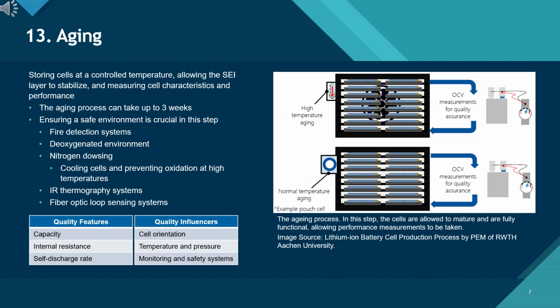Step 13 for aging. In this step, the cells are placed in controlled storage to allow the SEI layer formed during formation to stabilize. This maturing period is essential because the SEI continues to evolve, and its stability directly affects capacity retention, internal resistance, and long-term safety. Aging can take several days to as long as 3 weeks, depending on the cell type and manufacturer requirements.